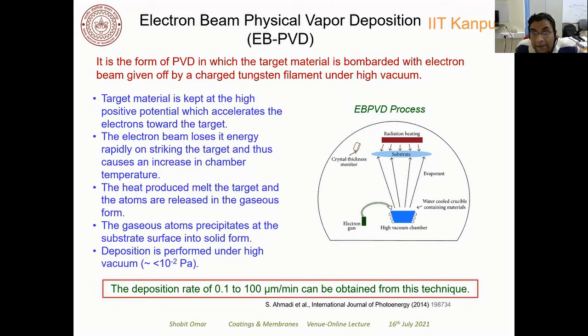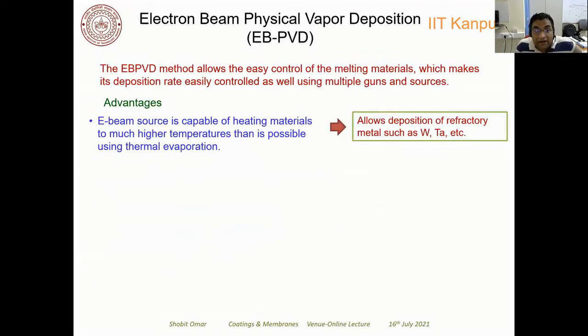technique. Now, the important advantage of E-beam physical vapor deposition is that you can go to very high temperatures, because you are locally heating your target material. So this technique can allow deposition of refractory metals such as tungsten, tantalum. This is one of the main advantages of using electron beam physical vapor deposition.